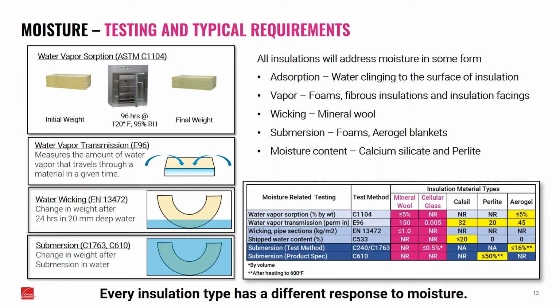Again, you'll see that as not a formal ASTM requirement, but something that's shown up in the industry, particularly around mineral wool pipe sections. And then finally, you have a submersion test, where you put the product itself underwater for a given period of time. You do a weight before and a weight after, and you determine how much weight it's picked up, typically as a percentage. So we go over here to this table on the lower right-hand side.